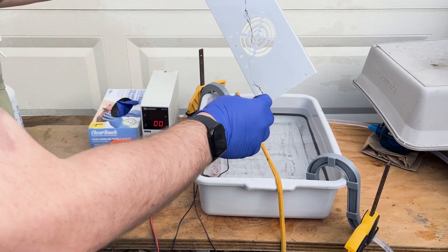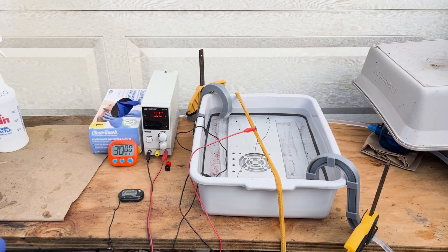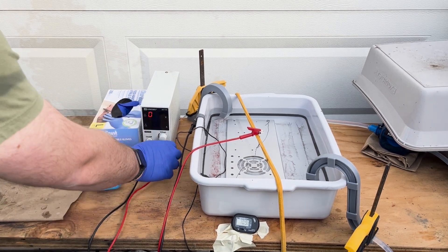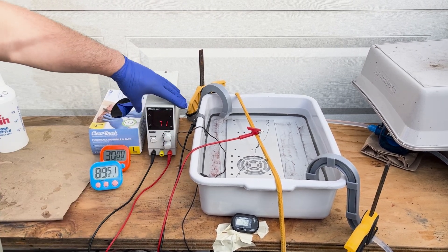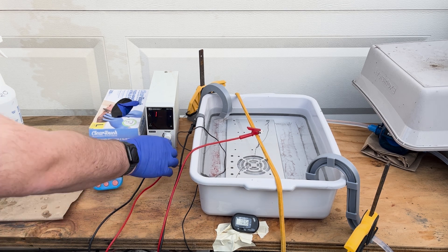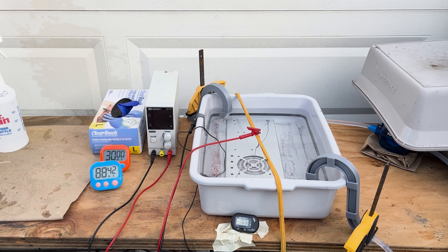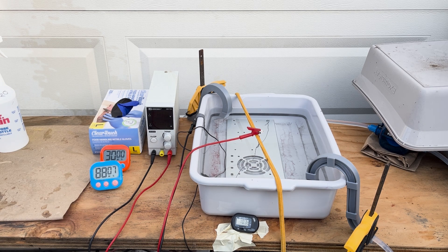After all that prep, we come to the actual anodizing step. Each panel will anodize for 2 hours. I call this type 2.5 anodizing — I can't cool the solution enough to do actual type 3, which is done around 0°C, up to around 4 degrees if I recall correctly. The pump you're hearing is moving the electrolyte out of the tub and through a tube, which is coiled and submerged in another tub of very cold salt water. I use an old chest freezer to extract the heat generated by anodizing, so the electrolyte stays under about 10 degrees Celsius. The colder temperature makes for a slower process but a much more dense and tough coating than room temperature anodizing would produce. This footage is sped up about 5 times. I'm just slowly ramping up the current over the first 5 minutes — that makes for a more even coating.